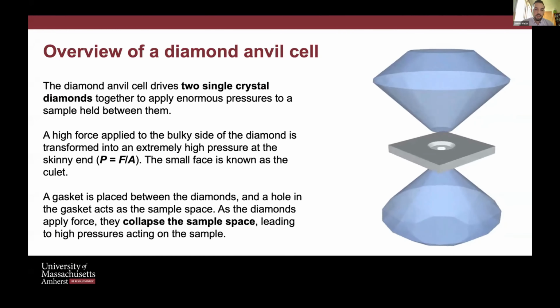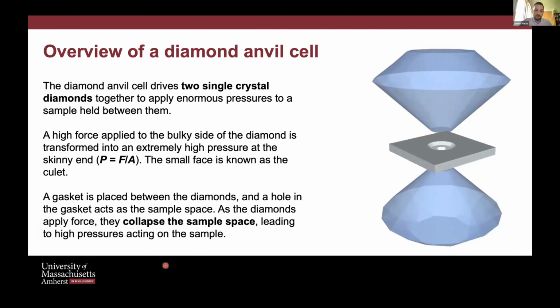Okay, so I'll start, as I always do, with a quick overview of what the diamond anvil cell is. This has already been touched on, but despite the complexity of all these different types of cell, the shapes of the cell and the conical opening and everything else, they all boil down to really just driving two diamonds together in a very aligned, precise way. You want a uniaxial force to bring the diamonds together, and you want them to not slip or tilt. If you can achieve that, you can do a high pressure experiment.